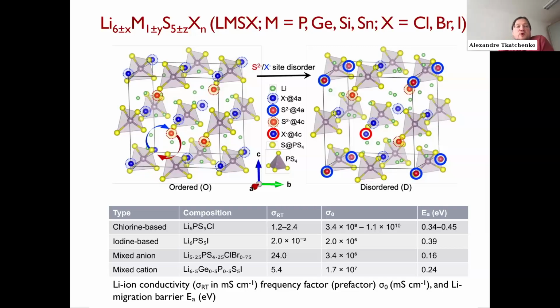Okay, yeah. So what I would do is I would just construct a machine learning force field using the HSE plus MBD forces as an input. I think that's what I would recommend. As Mariana has discussed in her talk, the speed of HSE plus MBD calculations is sufficient to generate enough reference data to construct machine learning force fields for these materials.